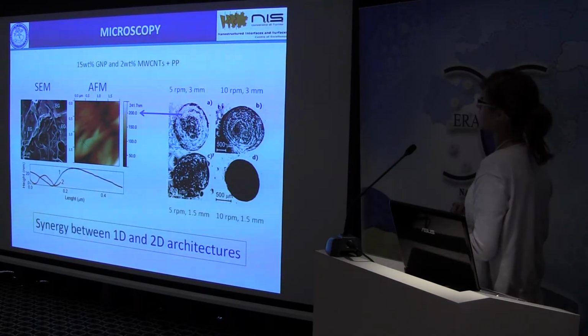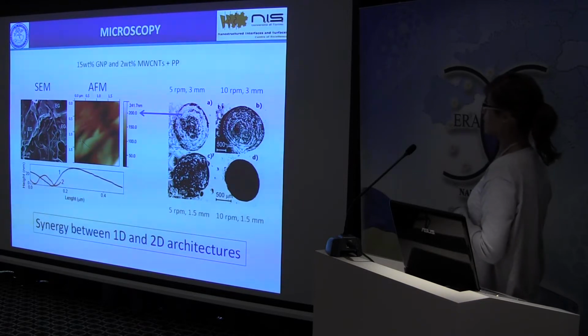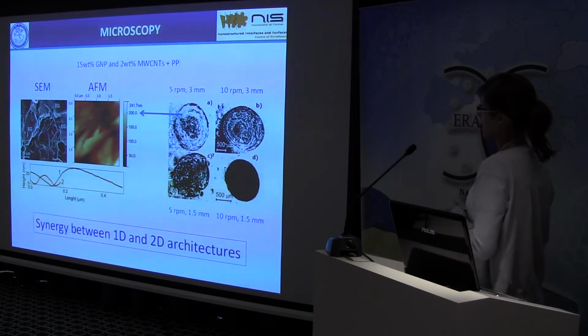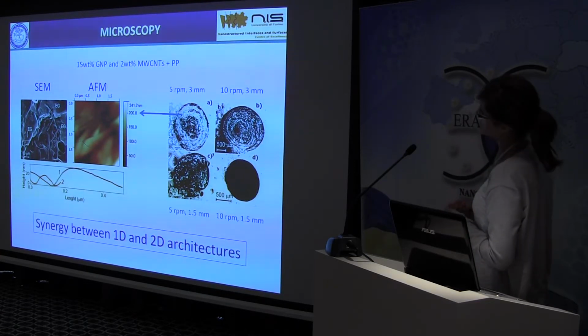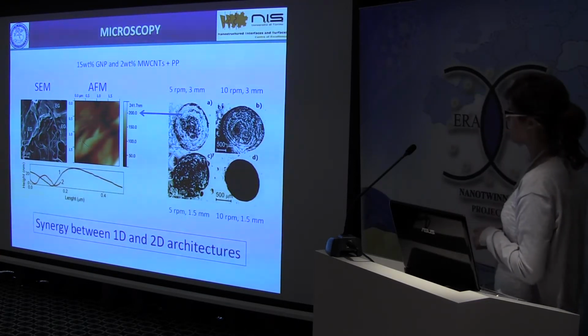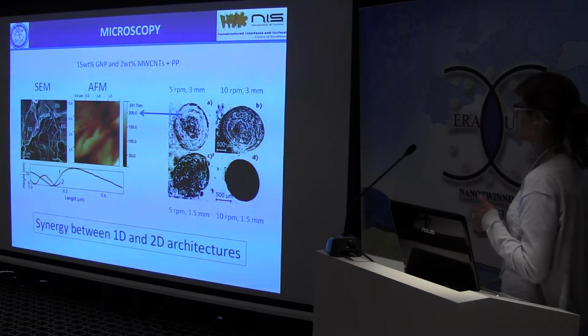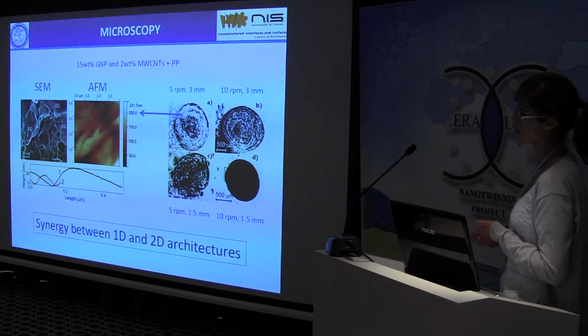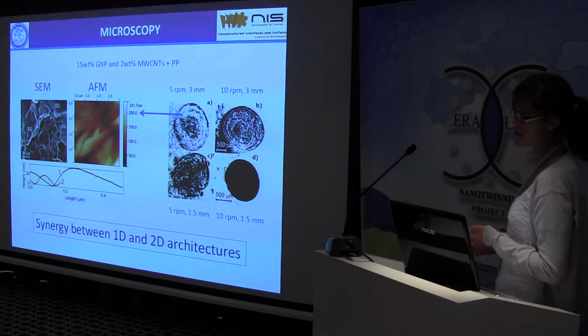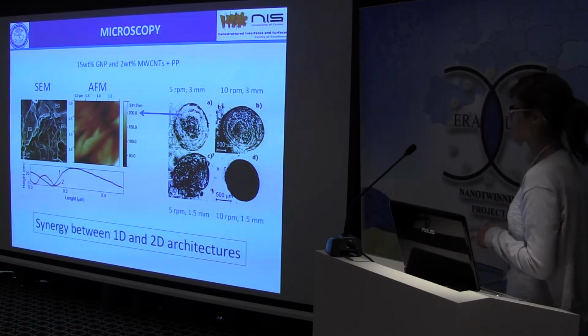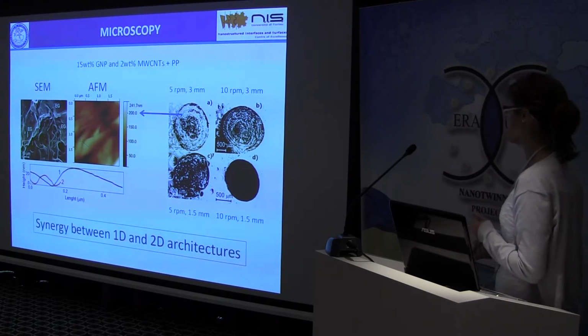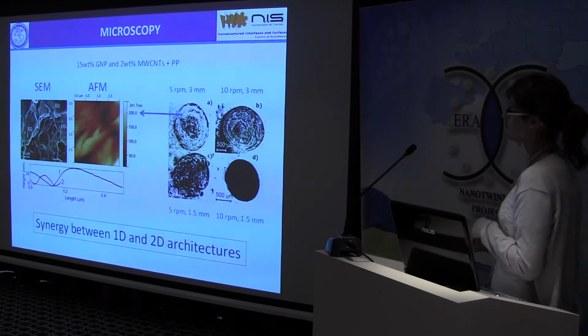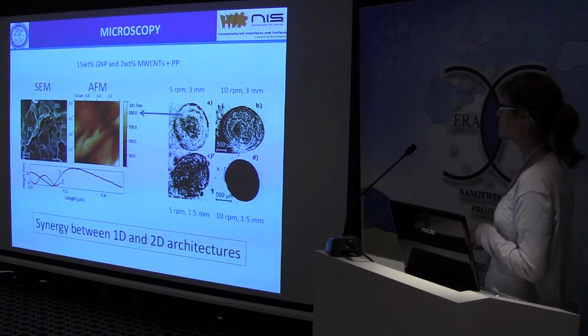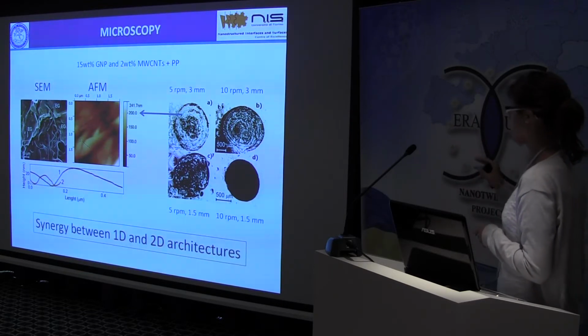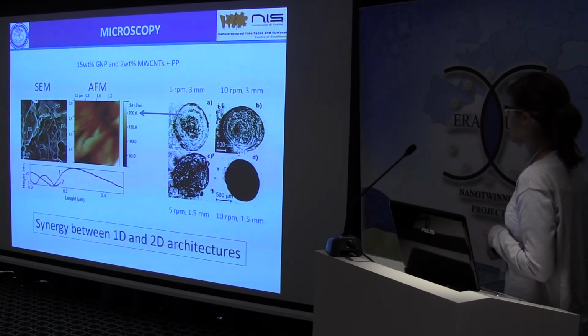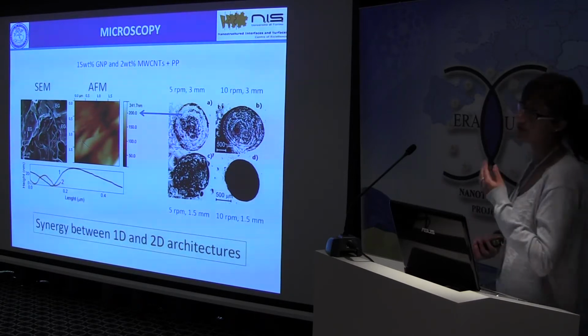The composite containing both multi-wall carbon nanotubes and graphite nanoplatelets was analyzed by scanning electron microscopy and atomic force microscopy. But first of all, we applied a non-conventional scanning electron microscopy technique called low voltage SEM. In this technique, the acceleration voltage of the electrons is very low, and by detecting the secondary electrons, we were able to obtain the images on your right, which are charge contrast images.